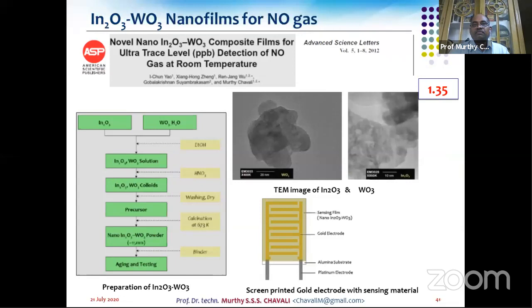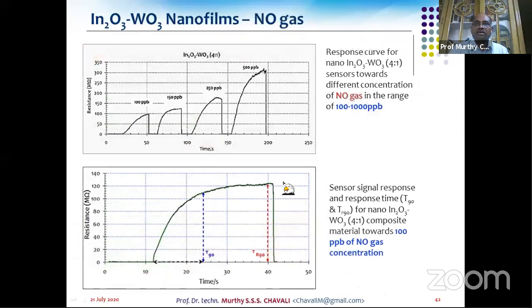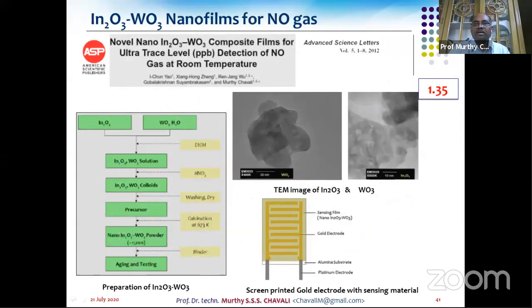And then we thought of developing a nitrogen dioxide sensor. We have very good results using indium oxide and tungsten oxide, dual metal oxide nanofilms over this particular electrode. All these materials have been prepared by the hydrothermal method. We ended up developing an NO sensor instead of an NO2 sensor. For NO2, later we reduced the indium oxide percentage, which is 1:4. Using CNTs, multiple CNTs and tungsten oxide, we were able to develop a different sensor for NO2 gas. The typical sensor dynamics are in the range of 100 to 1000 ppb, where you can see these particular gas dynamics. And perfectly, this is aligned with NO gas rather than NO2 gas.